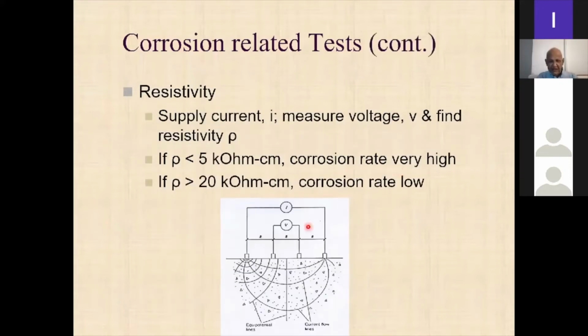Here you supply a current and then you measure the voltage, and then you can get what is called the resistivity in ohm centimeters. If it is less than this, corrosion rate will be very high. If it is greater than that, corrosion rate will be very low. So the basic thing for this is, if your concrete is very dry, and if you are confident that you can maintain it at that dry state, then even though your depth of carbonation has gone past the reinforcement, you don't have to worry so much, because the resistivity is high and the corrosion rate will be quite low. Okay.